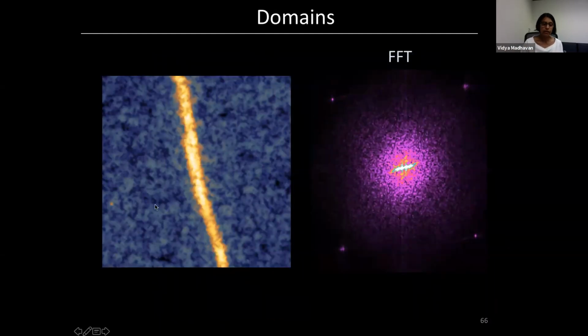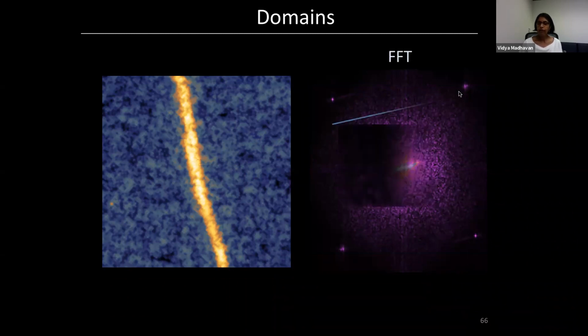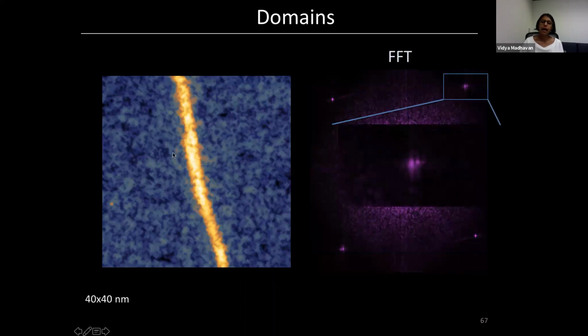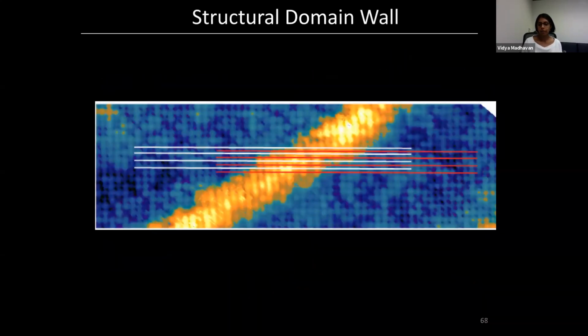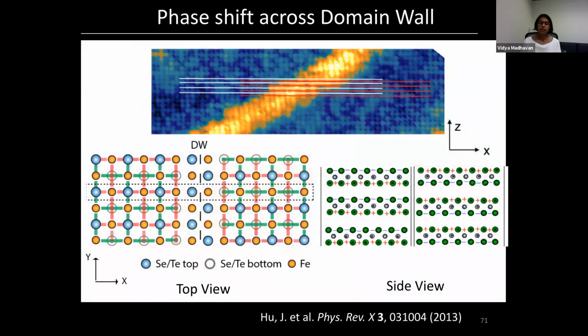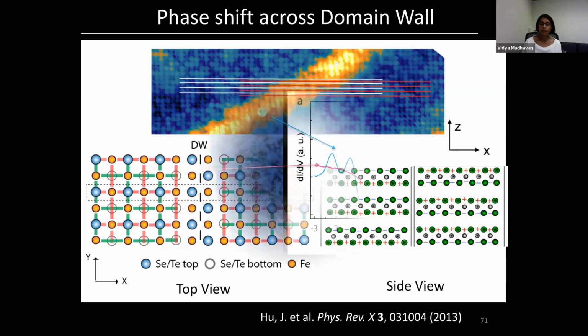So if you look at this kind of a region and you take a Fourier transform, what you find is that there's only one peak, but if you zoom in here, you find that there's a splitting of the Fourier transform peaks. And what that basically tells you is that the atoms on one side and the atoms on the other side are phase shifted with respect to each other. You can use your eye to track the atoms on one side and the other side. In any case, whatever method you choose, you can show that the atoms on the two sides are phase shifted with respect to one another. So this is the ideal condition to get this pi phase shift in the superconducting order parameter.